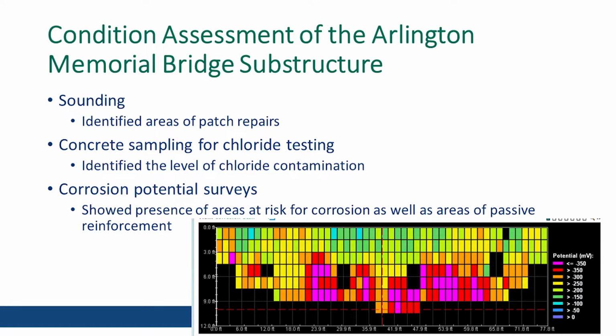So the other thing we needed to do was look at where corrosion is going to be active in the future, so that we can prevent it from causing concrete deterioration. We did chloride testing, concrete sampling, and corrosion potential surveys to look at where the risk for corrosion was high. Comparing where the damage is now and where the damage is moving, we can then provide a more effective durability and service life extension.